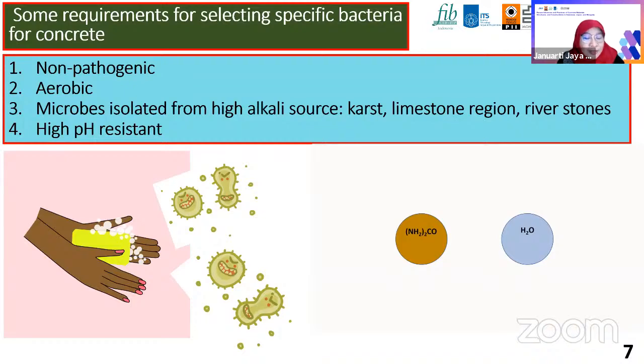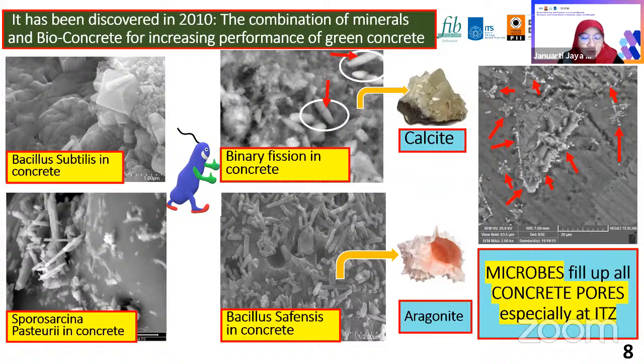We have found that some local bacteria in Indonesia can be very much useful to increase the concrete performance. We have Bacillus subtilis, and we have also the Bacillus Safensis to produce calcite here. And also, we can even find aragonite in concrete pores. It is a very hard material and it's a very strong material. It fills the interfacial transition zones in concrete, so there is no gap between the aggregates and the concrete matrix. We were lucky once during the SEM analysis, we captured the binary fissions of the bacteria inside the concrete.